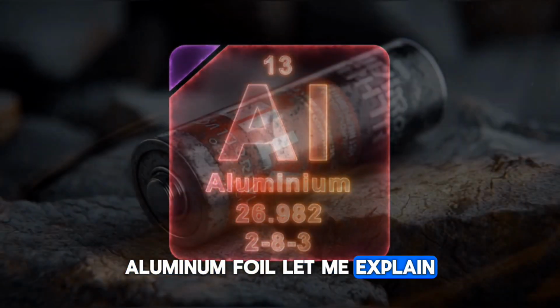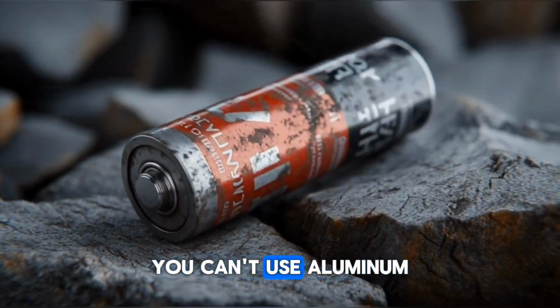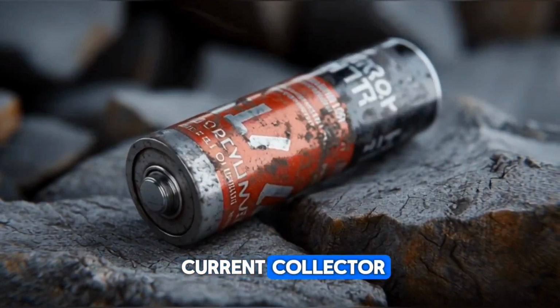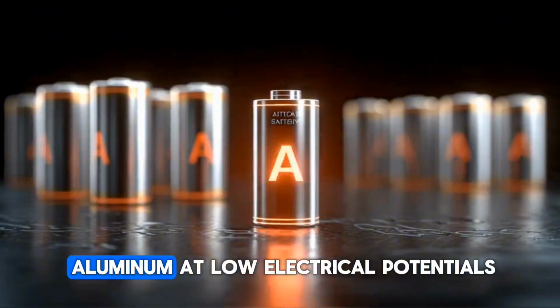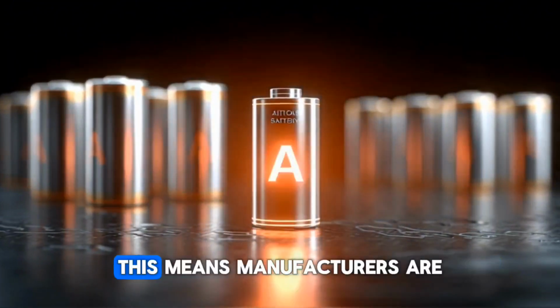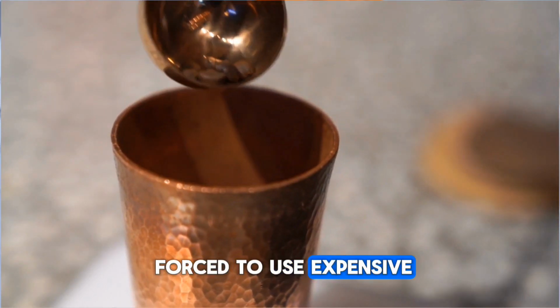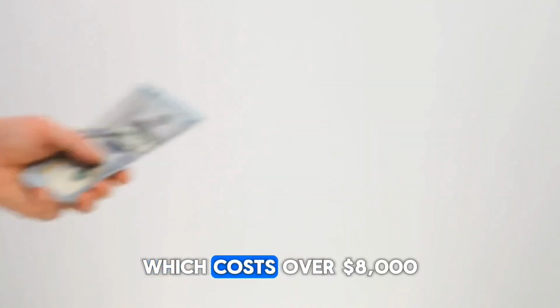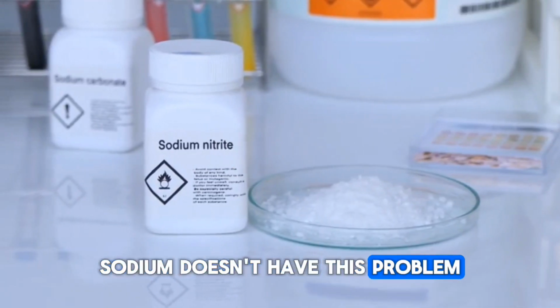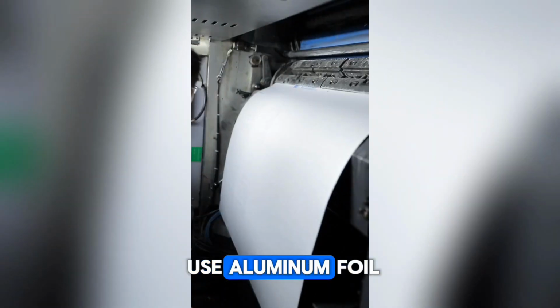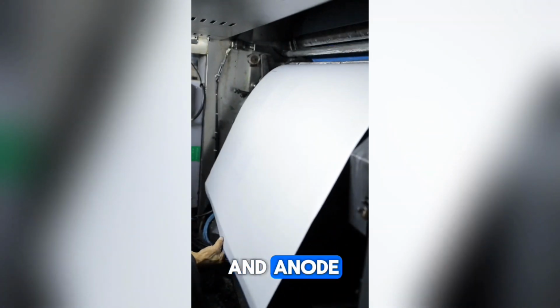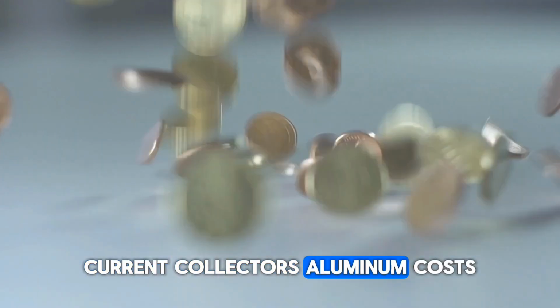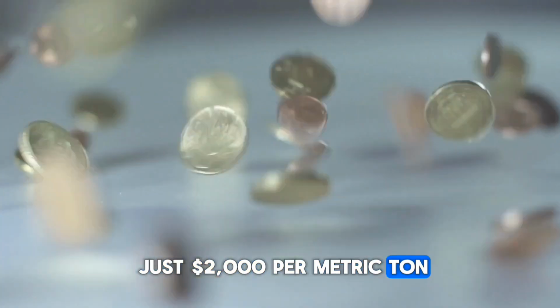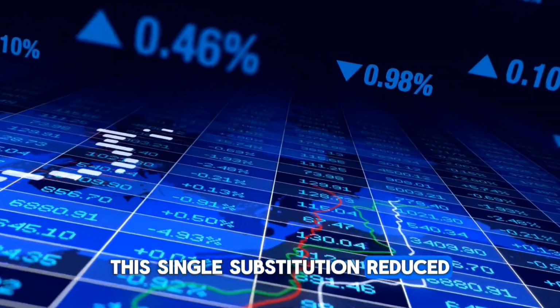Let me explain. In lithium-ion batteries, you can't use aluminum foil for the anode current collector because lithium alloys with aluminum at low electrical potentials. This means manufacturers are forced to use expensive copper foil, which costs over $8,000 per metric ton. Sodium doesn't have this problem. Sodium-ion batteries can use aluminum foil for both the cathode and anode current collectors. Aluminum costs just $2,000 per metric ton. This single substitution reduced current collector costs by nearly 50%.